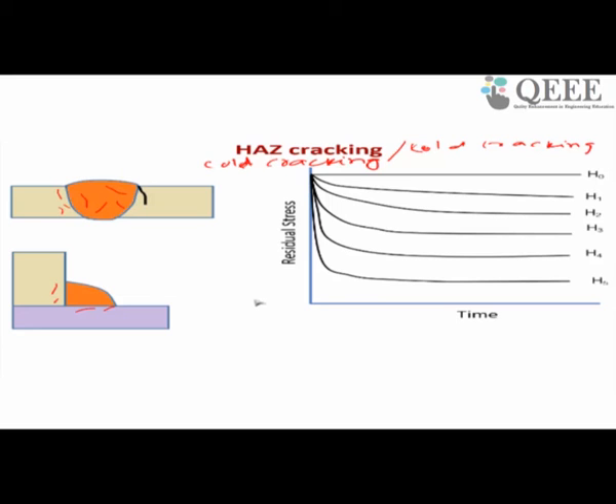hydrogen will not be able to come out because of rapid solidification or a very high cooling rate. If it does not come out, it will be entrapped inside the material. It may be entrapped inside the weld pool, or it may try to escape and you will get porosity, or it may go to the nearest zone, the heat affected zone. There it will be entrapped. Hydrogen is an interstitial atom, so it may be entrapped between two atoms, like this.